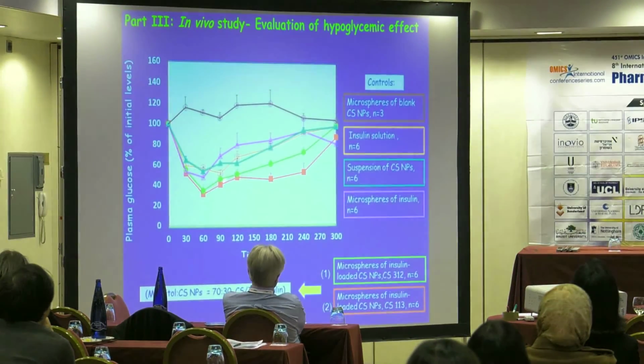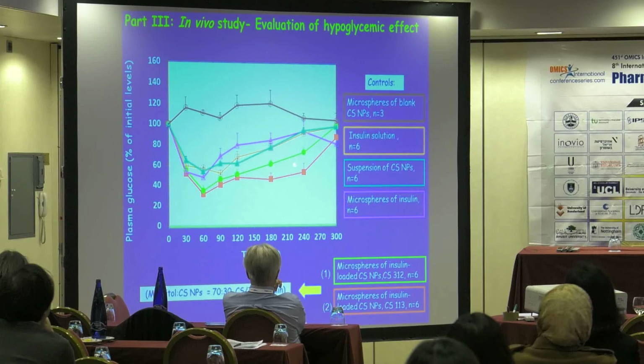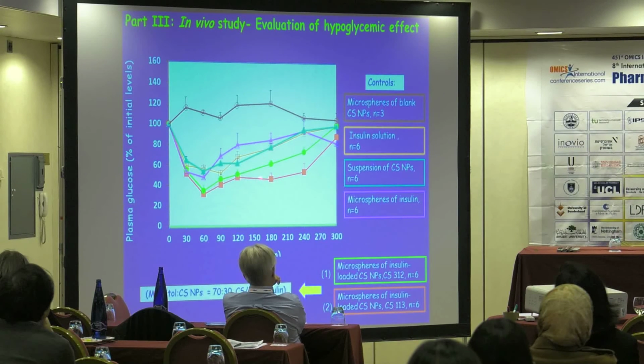Here we have the microencapsulated chitosan nanoparticles with two different molecular weights of chitosan, compared with the control formulations, which showed a significant hypoglycemic effect. However, this hypoglycemic effect was prolonged and more pronounced for the microencapsulated chitosan nanoparticles with a molecular weight of 113.